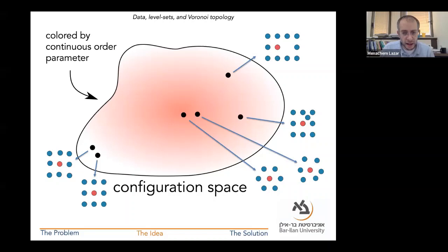And the classification would happen when maybe we'll choose a cutoff. If you remember those cutoffs that I used when I showed the picture, you'd say any arrangement of particles that has a centrosymmetry value of under 0.2 or whatever it was, we should classify as being a crystal.